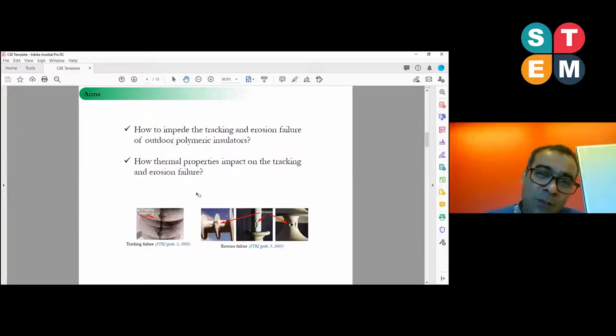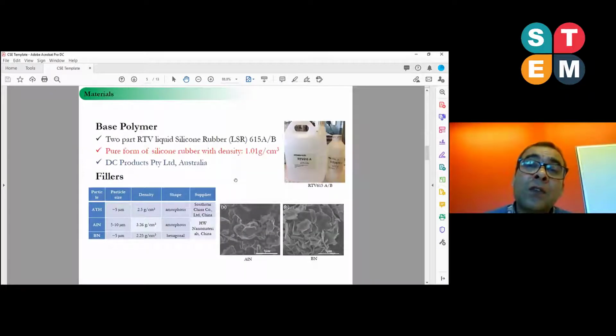The aims are how to impede the tracking and erosion failure of outdoor insulators, and how thermal properties impact tracking and erosion properties, because they are directly correlated with the leakage current amount and how much heat is accumulated on the surface of the insulator. Silicone rubber is usually used for outdoor insulation because the polymer is highly hydrophobic and flexible. In pure form, silicone rubber cannot be used as an outdoor insulator because the mechanical strength is not good enough, so we usually have to use some inorganic additives in it.